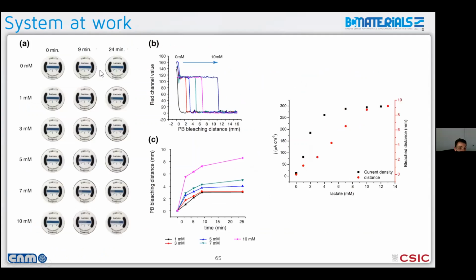Okay. So then what we did with the complete devices, I think we're running a bit late maybe, but we're almost there. We made a lactate biosensor and connected it to the display. And we looked at how the color was changing depending on the concentration of lactate and the time of contact between the biosensor and the sample. What we found was very sharp, and this was unexpected, very sharp color changes.